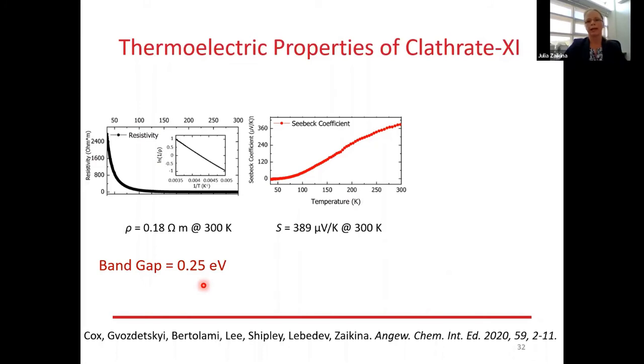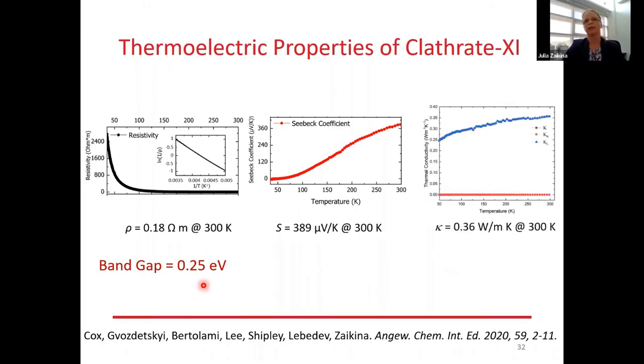But we also want to have a material which is a poor thermal conductor, a material which has very low thermal conductivity, similar to glass. And this is indeed what's happening with this clathrate compound. It has this extremely low thermal conductivity comparable to the glass SiO2, amorphous SiO2, and so we think that this is due to the complexity of the structure, but also due to the rattling of the potassium cation inside these large cages in the clathrate structure.